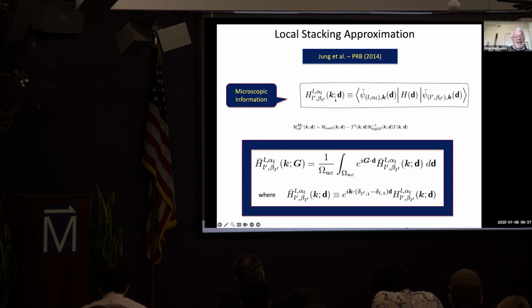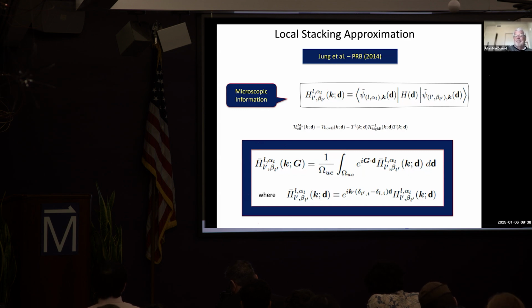Because the other layer is far away, the dependence of the Hamiltonian on that parameter as you move it will be smooth. And because it's smooth, it's natural to Fourier transform it. The non-constant terms, the dependence on D, this Hamiltonian is basically periodic in D. And so if I Fourier transform it, I only get coefficients at reciprocal lattice vectors. And what I'm really arguing is that typically it's only the first shell of those reciprocal lattice vectors, the smallest momentum transfers, that are significant.